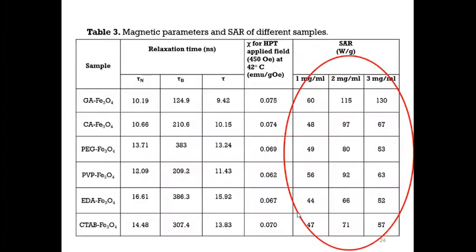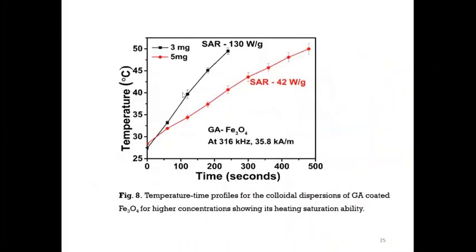So this is our comparison. The glutamic acid coated sample possesses very good properties compared to the other one. This depends not only on the shape and size, but also on its susceptibility, its magnetization, as well as the effective anisotropy. All right. For the same glutamic acid, if we again increase the concentration, it shows heating ability with respect to the concentration, and if you increase the concentration beyond 3 mg, the SAR value decreases to 42 watt per gram. This is the power dissipated per mass of the particles. At the same applied frequency and same field strength, we get a decrease in the SAR values, and hence it depends on the concentration too.